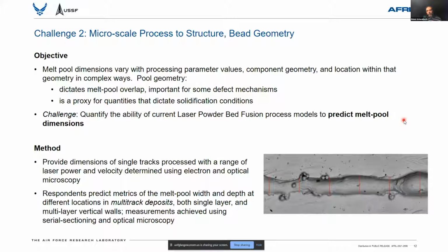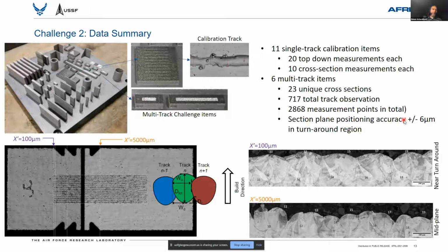So here, the calibration data consisted of measurements of individual tracks that were deposited using different powers and speeds. And then the challenge question focused on multi-track deposits. So if I switch to the next picture, you'll see a build here that actually looks fairly familiar. In the previous challenge, we were focused on some of these walls. I'm now focusing in on a pad that contains a series of single tracks, which are our calibration items. And then the multi-track items, which consist of a block that was built up as effectively a substrate, and then a series of tracks that were laid down on top of that block in a single layer in this case.